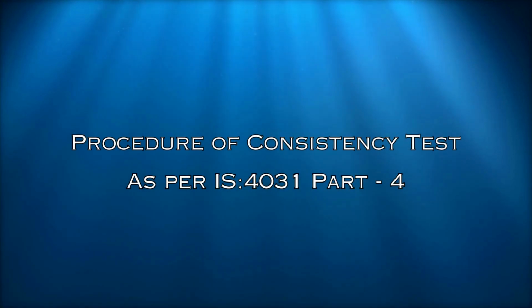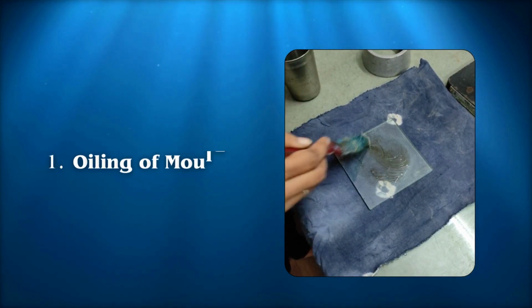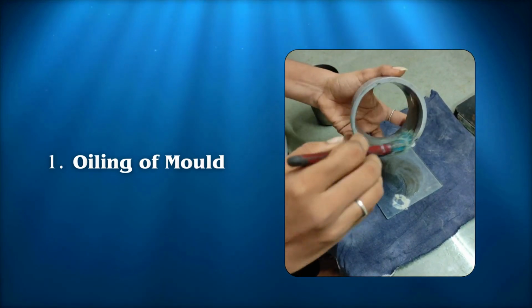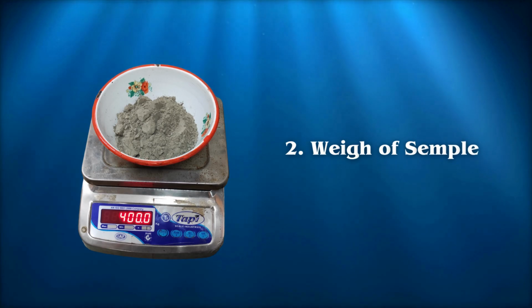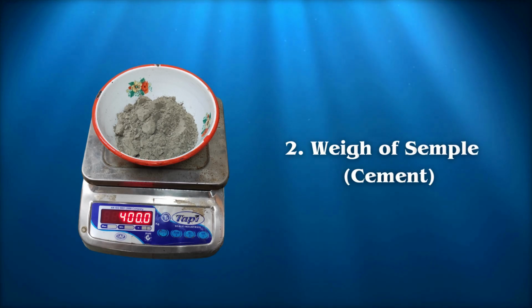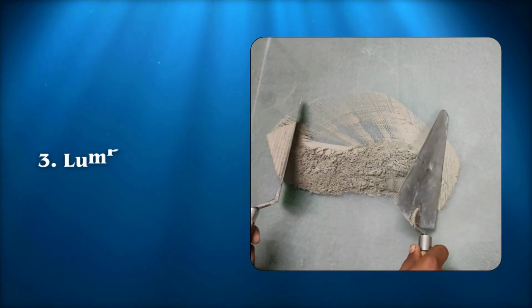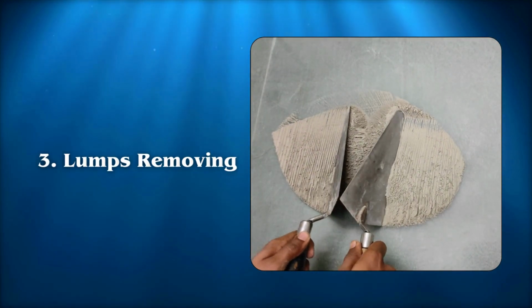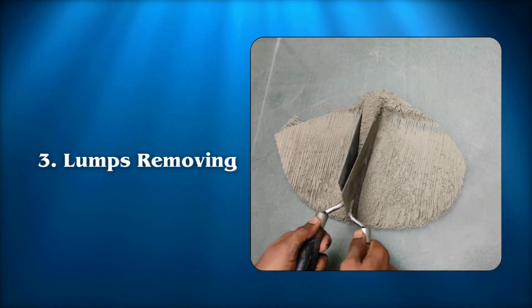Here's the procedure for the consistency test of cement, following the specified sequence of steps. Firstly, begin by oiling the Vicat mold to prevent the cement paste from sticking to it during the test. Carefully take approximately 400 gm sample of cement and ensure it is free from any lumps or impurities by using a gauging trowel.